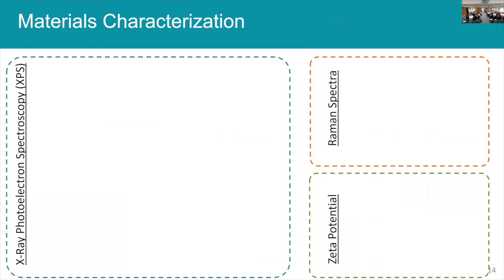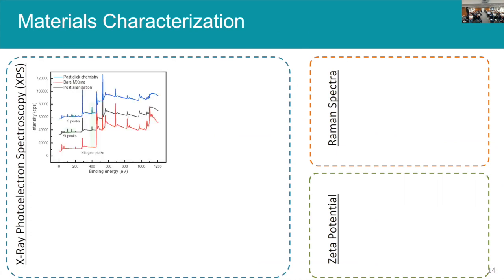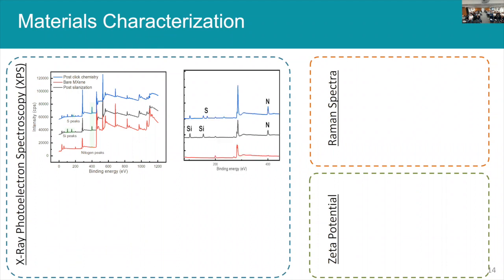XPS is a really, really cool elemental composition materials characterization technique, where you can actually see all the elements, even the bonds on the surfaces. So we did XPS to look at the bare MXene in red, post-silanization in black, post-click in blue. I don't want to spend too much time, but I'll just highlight a few cool things. With the bare MXene compared to the silanized MXene, you see the appearance of silicon peaks. So great, we definitely have silicon on the surface. You also see the appearance of nitrogen peaks.